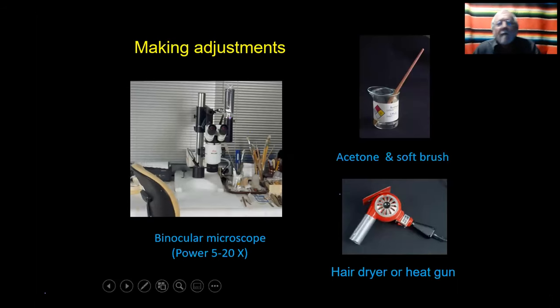You need a binocular microscope to check your joins. Doesn't need to go to very high power. So just 5 to 20 maybe is all you need. But it's amazing what you see under the microscope as to whether your join is perfectly lined up or not. You can look at weathering, you can look at scratches, you can look at air bubbles, you can see a lot of detail just under that kind of magnification.